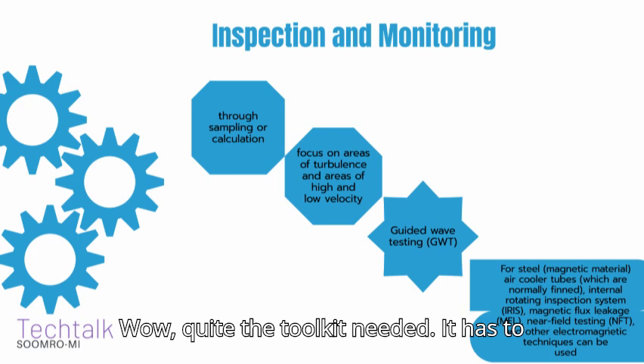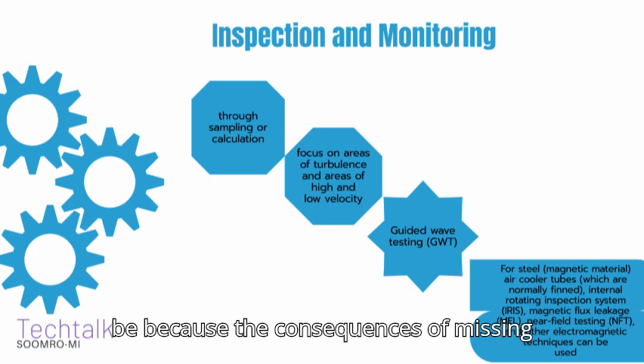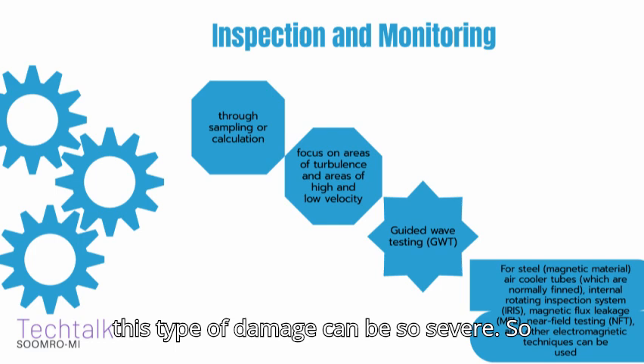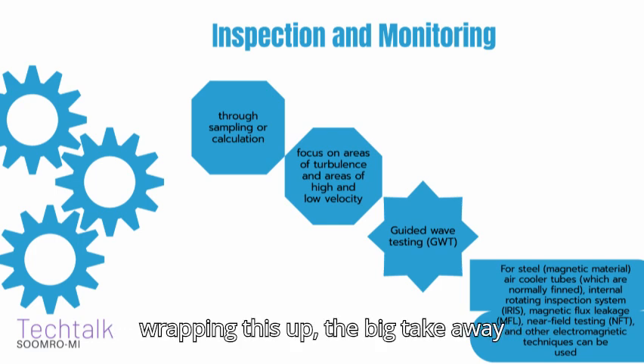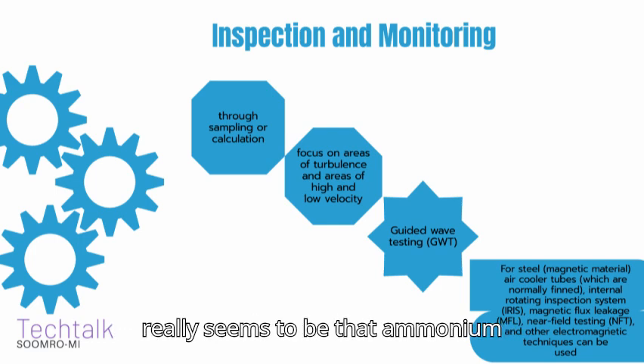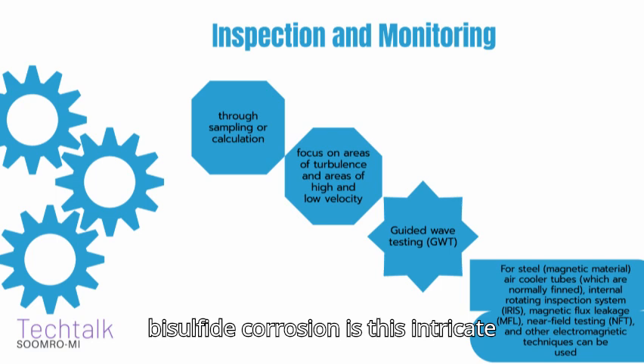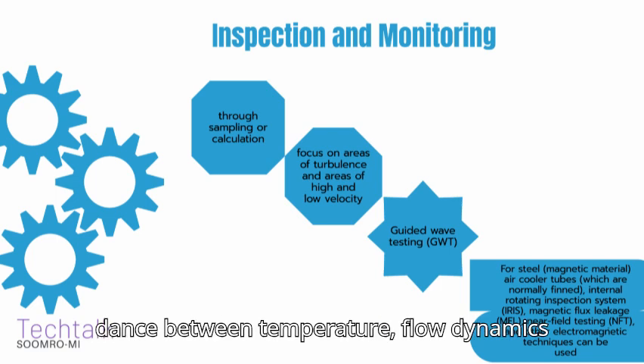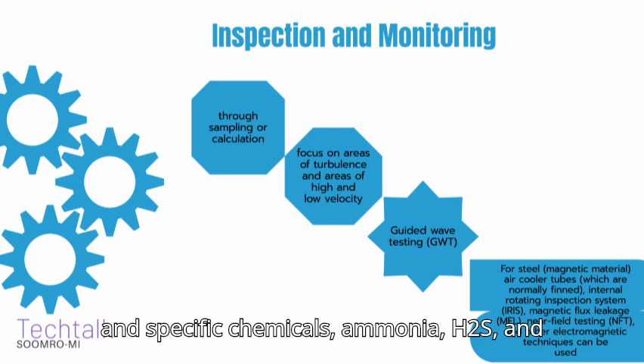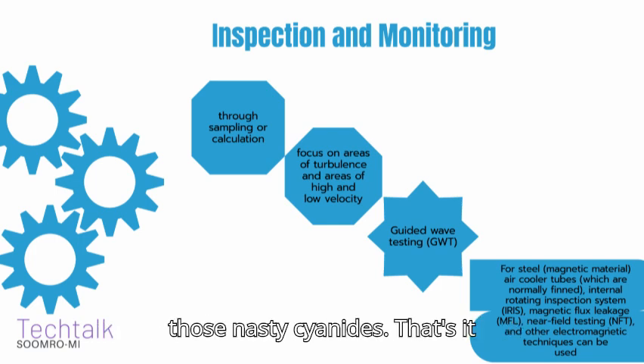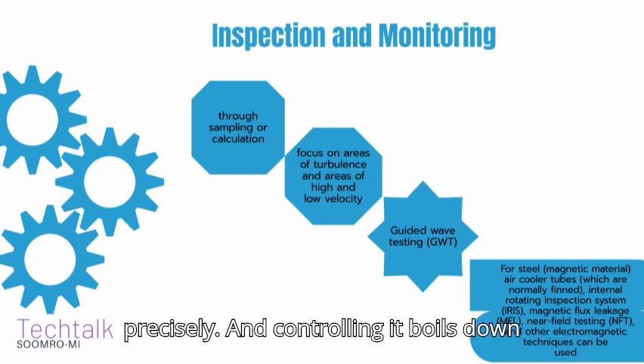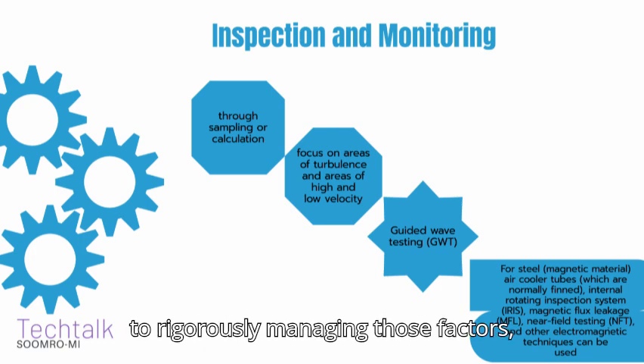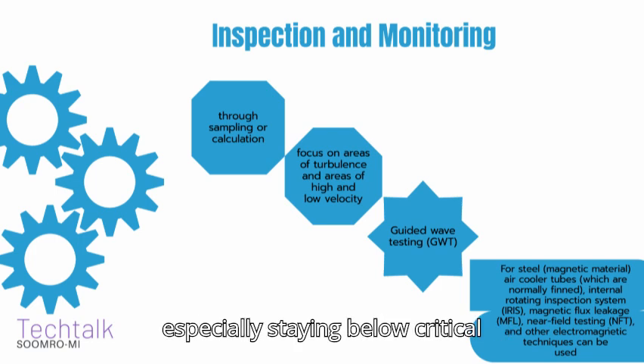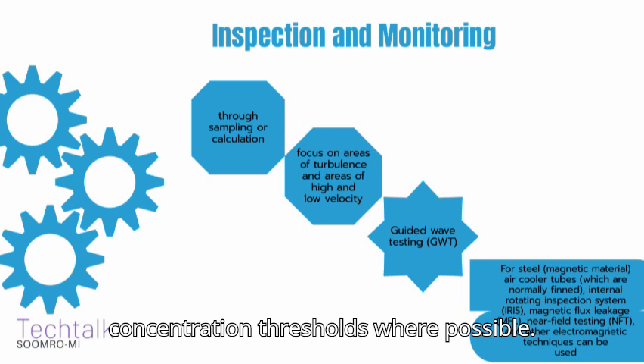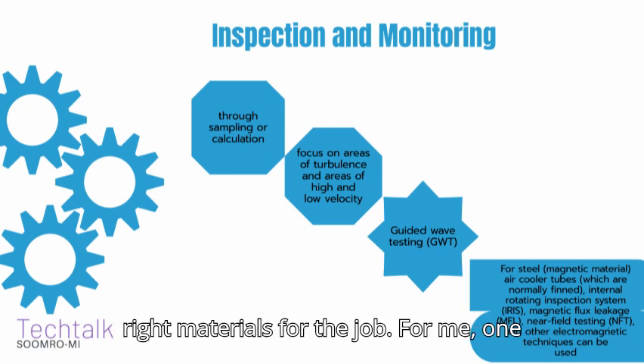Wow, quite the toolkit needed. It has to be, because the consequences of missing this type of damage can be so severe. So wrapping this up, the big takeaway really seems to be that ammonium bisulfide corrosion is this intricate dance between temperature, flow dynamics, and specific chemicals: ammonia, H2S, and those nasty cyanides. That's it, precisely. And controlling it boils down to rigorously managing those factors, especially staying below critical concentration thresholds where possible, controlling velocities, and choosing the right materials for the job.